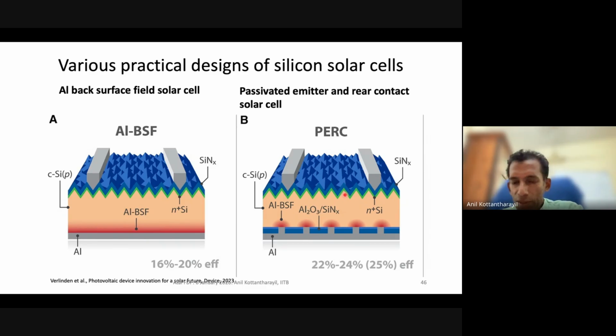Here, PERC, the only difference is everything else here is all the same. The backside has some difference. You have an aluminum oxide silicon nitride layer deposited on the entire backside, and then you open small windows by laser ablation of this dielectric. Then you put aluminum on the backside, and the aluminum makes contacts through these windows, the openings in this aluminum oxide silicon nitride stack. So this essentially provides higher efficiency than this, because the backside is not very well passivated in this case, because this backside is directly in contact with the metal, where the surface passivation is very poor. And instead of that, here you have an interface between the semiconductor and the dielectrics, aluminum oxide and silicon nitride. So that provides very good passivation. This contact area would be about 1 to 2% of the total backside surface area.